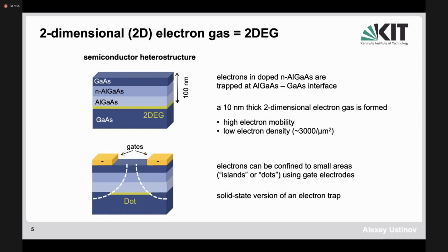And then you place on top metallic gates such that you could push away electrons by Coulomb forces from the area below the gates. So by pushing away, you leave a two-dimensional electron gas only in this location here. So they are pushed away from here and from there. So only here you will have electrons in the two-dimensional electron gas. And then if you make this little island very small from other directions in this two-dimensional topology, then, of course, you have a quantum dot.